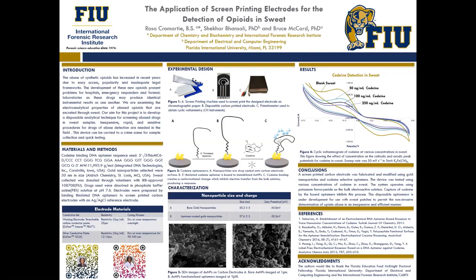And in the table that you see below under characterization, we were able to characterize the gold nanoparticles by size and charge, comparing bare gold nanoparticles with aptamer-coated gold nanoparticles. And it can be seen that the size of the aptamer-coated gold nanoparticle increases when compared to the bare gold nanoparticle. This change in size demonstrates the addition of DNA, because we're able to see that DNA became bound to the gold nanoparticle because of the strength between gold and sulfur from the thiolated aptamer, creating a high binding energy.